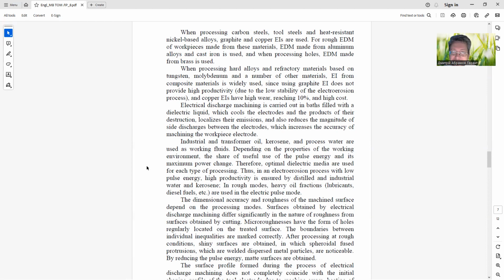When processing hard alloys and refractory materials based on tungsten, molybdenum, and a number of other materials, EI from composite materials is widely used, since using graphite EI does not provide high productivity due to the low stability of the electroerosion process, and copper EIs have high wear reaching 10% and high costs.